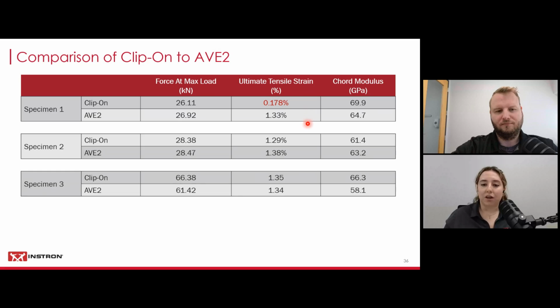For specimen 2, those percentages look pretty good in terms of being close to one another. I'm sure if our equipment was verified, those would be even closer. And specimen 3 is awesome. Only 0.01% off. That's what I want to see. Now my chord modulus for specimen 1 actually came out lower in my AVE2 by about 5 gigapascals. For specimen 2, it came about 2 gigapascals lower with the clip-on. And then for specimen 3, it came about 8 gigapascals higher with the clip-on as compared to the AVE.